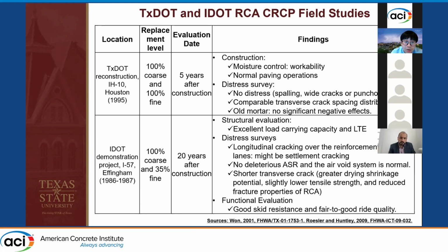And for the distress surveys, they found there are a few longitudinal cracks on the RCA sections, and they concluded that it might be settlement cracking due to the reinforced rebars. And also, they did not find any ASR problems, and the air void system of the CRCP RCA section was great. And they did find shorter transverse cracking spacing, and it was primarily due to greater drying shrinkage potential of RCA concrete, and also the lower tensile strength and reduced fracture properties of the RCA concrete. For the skid resistance, they found it was satisfactory, and also they reported fair to good ride quality of the RCA concrete pavement.